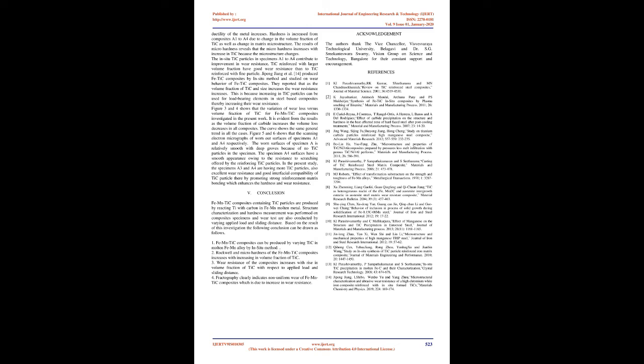Haipen-Zhang et al. 14 produced Fe-TiC composites by in-situ method and studied the wear behavior of Fe-TiC composites. They reported that as the volume fraction of TiC and size increases, the wear resistance increases. This is because increasing TiC particles can be used as load-bearing elements in steel-based composites, thereby increasing their wear resistance. Figures 3 and 4 show the variation of wear loss versus volume fraction of TiC for Fe-Mn-TiC composites investigated in the present work.